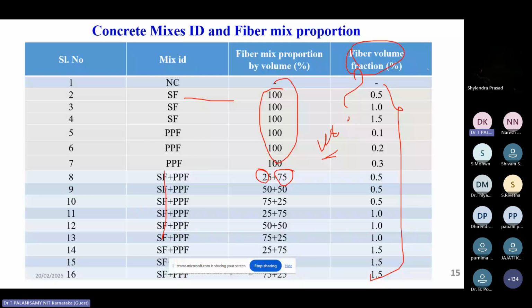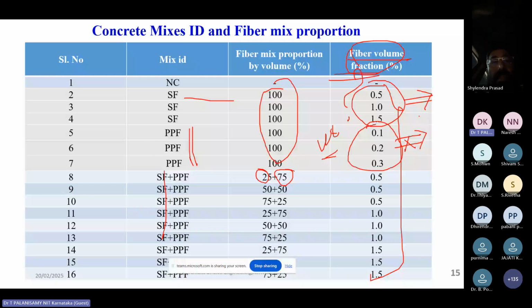Volume fractions are like 0.5, 1, 1.5. Here they use polypropylene fiber volume fraction of 0.1 to 0.3 alone. But in the case of steel, we can go higher. Usually a lot of workability problems arise when the volume fraction goes up, and I can get balling effects. The concrete is not sticky or flexible in nature; it is very difficult to mix and carry, and segregation happens between the aggregates, the cement mortar, and the fiber. For this reason, they are using these fiber volume fractions.